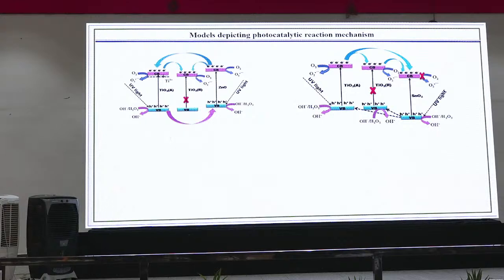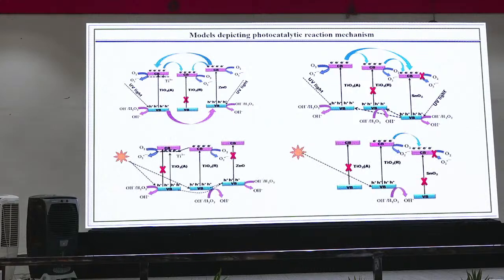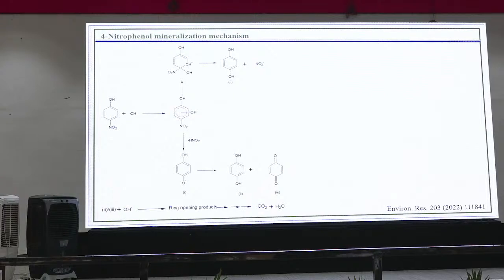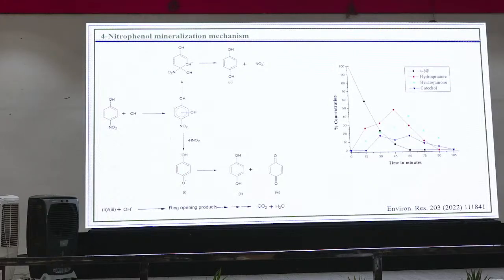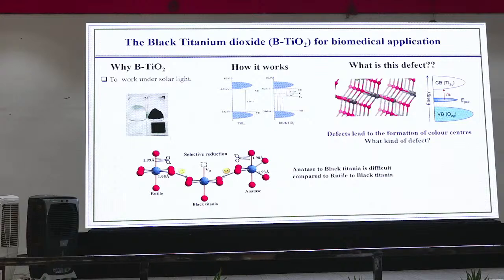Based on that, we developed the mechanism part: from where to where the electrons will go, and how it will work in UV light and visible light. Then finally, since I'm basically an organic chemist, I was interested in the degradation pattern, how the degradation was happening. For this we carried out GCMS analysis. Based on the GCMS analysis, we were able to predict the mechanism of degradation, how it has been degraded, at what time interval what intermediate was formed, and at what ratio it is there. That we also tried to analyze. And after that, till now I have done about the ternary heterojunction.